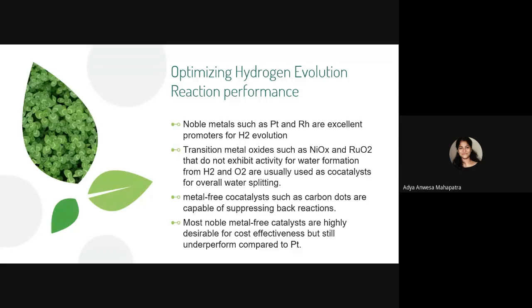Recently, an oxidized platinum cluster was also reported as an efficient hydrogen evolution reaction catalyst, and it also checked the undesirable hydrogen back oxidation. Nickel oxide, or even simply nickel, on carbon nanotube sidewalls also acts as a highly effective hydrogen evolution reaction electrocatalyst. It shows activity similar to that of platinum. But as platinum is a precious metal, new non-precious metal electrocatalysts are being tested for hydrogen evolution. For example, molybdenum disulfide has been studied as an electrocatalyst for hydrogen evolution reaction, and it showed high performance.